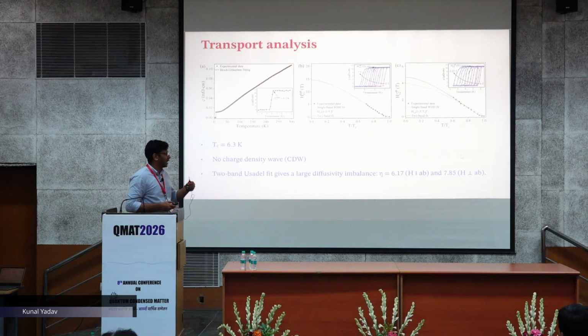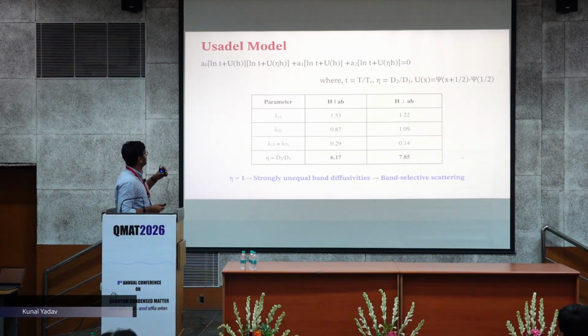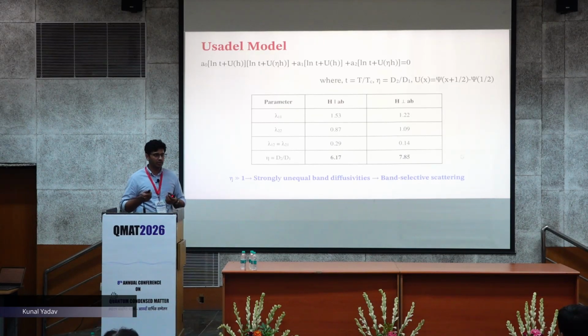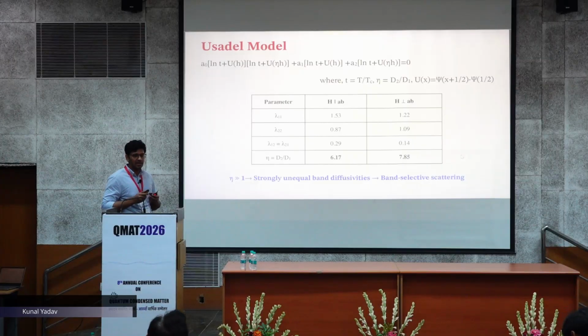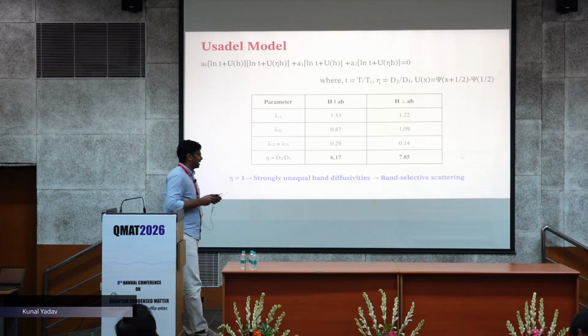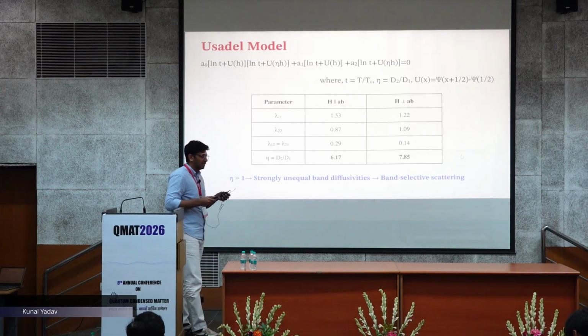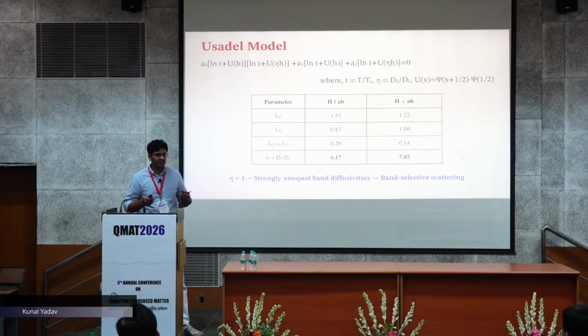This is important. I will tell you why. Because the Usadel model is used to describe a dirty two band superconductor. This eta greater than 1 strongly indicates a strongly unequal band diffusivity. This means that this is a multi-band superconductor, and it has, you can say, two different bands.